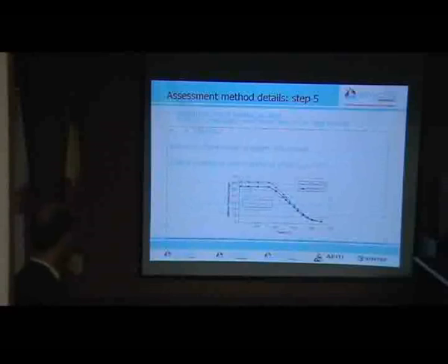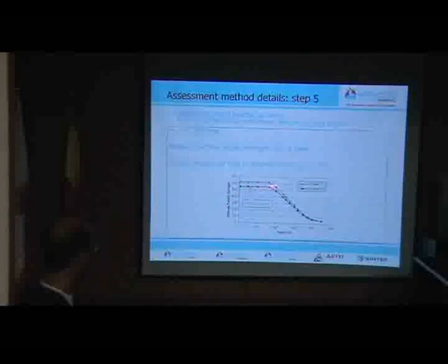This has to be compared with what we can allow, and then again we have to determine the critical heating up time. We can make a distinction between low tension and high tension. If you have a low tension, it's based on the yield strength of steel with these kinds of formulas. And when we have high tension, it's based on the ultimate tensile strength of steel, and this is the curve we used to determine that.